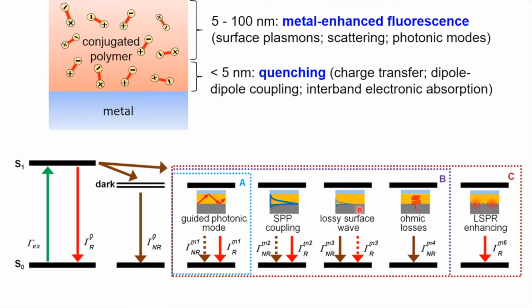Also, we could get coupling to lossy surface waves or ohmic losses, in other words, absorption in the metal, and this would increase the non-radiative rate. Finally, if we structured the metal, as we would with making nanopores or particles on the metal surface, we can increase the radiative rate through localized surface plasmon resonances interacting with the excitons. So there are many different pathways for excited excitons in materials to decay besides the regular transition when they're coupled to metasurfaces.